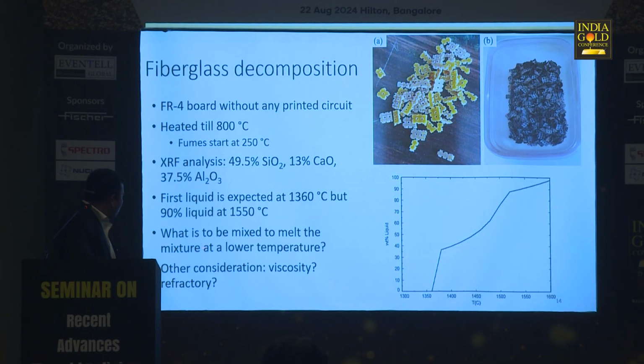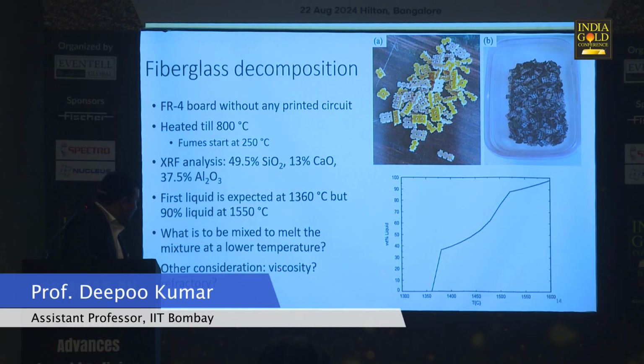So then the goal was, what can we mix to lower the temperature? If you look at literature, at least at research scale, people tried mixing boric acid and so on. But there are two concerns, at least to start with. One is, of course, it should have enough liquid fraction at low temperature, as low as 1100, 1200 Celsius. And it should have sufficient viscosity so that it allows the percolation of your metallics from this thing.